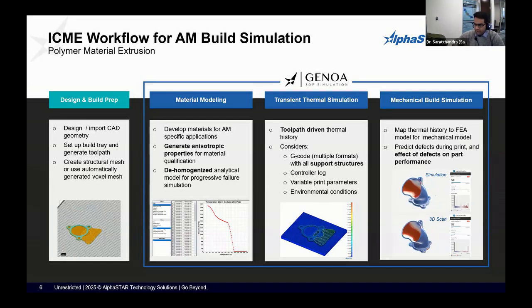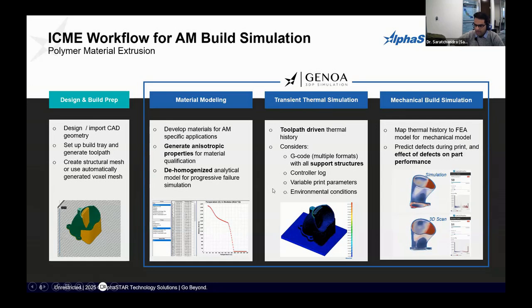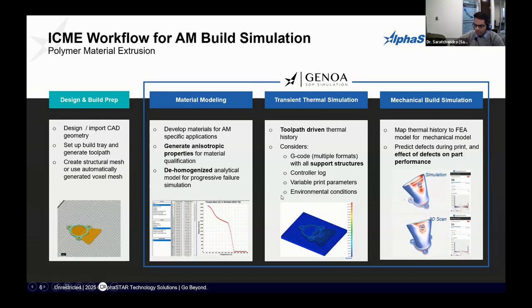And to simulate the build process itself, we use a two-stage approach. We start with a transient thermal simulation, which is toolpath driven. It's not layer by layer. It is a time-based solution which follows the toolpath sub-layer. So it results in a much higher resolution and a much more accurate time temperature history. It considers the GCode and if there are any support structures, rafts, stabilizers, all those kinds of things, it is automatically picked up by our GCode translators. It picks up any controller effects, variable print parameters, and also your environmental conditions, your radiation, convection, and so on.